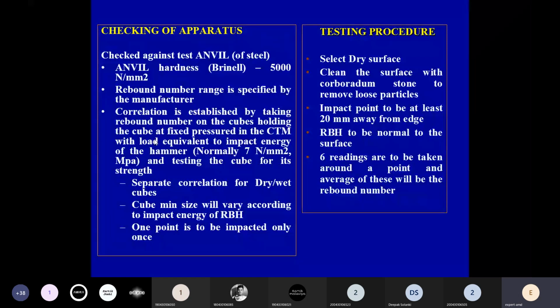After 28 days, we impact the hammer on the cube surface from all four faces, and we try to develop a relationship between the rebound hammer reading and your compressive strength for that particular project. In that case, the rebound hammer will have more accuracy compared to using the manufacturer's curve, because many of these hammers come from international manufacturers, and those manufacturers have a different set of materials and different environmental conditions when they are